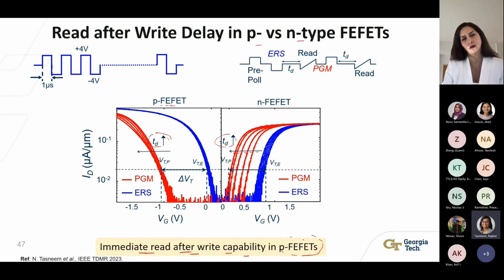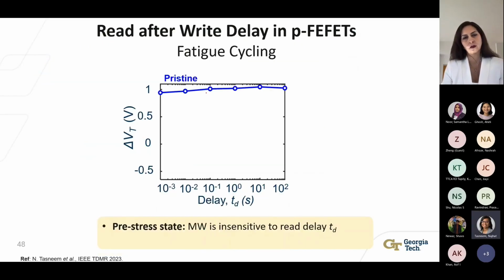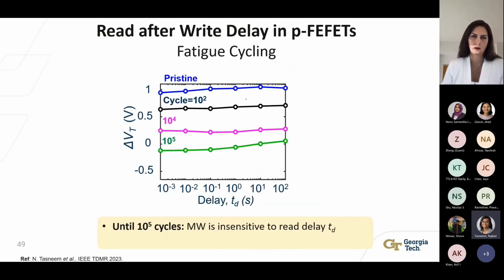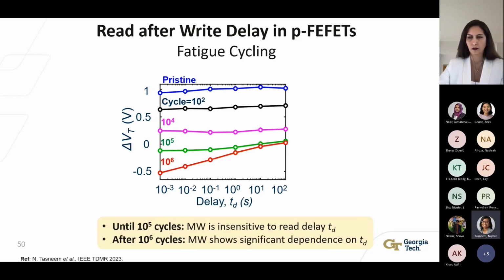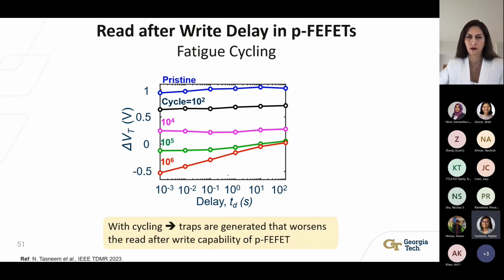So the results show that in pristine state, the memory window is independent of read after write delay in p-FEFET. And as we keep on cycling the device up until 10 to the power 5 cycles, the memory window is still independent of the read delay. However, after 10 to the power 6 cycles, when the memory window closes, it shows a significant dependence on the read delay, which means that p-FEFET has lost its immediate read after write capability. So this also indicates that with cycling, some sort of traps are being generated that is worsening the immediate read after write capability of p-type FEFETs.